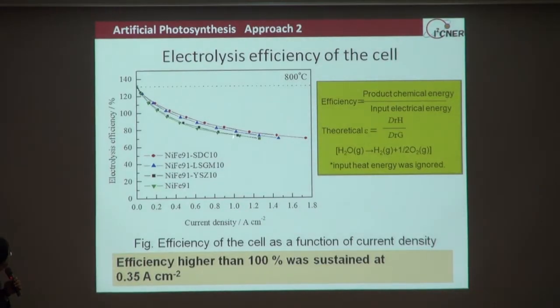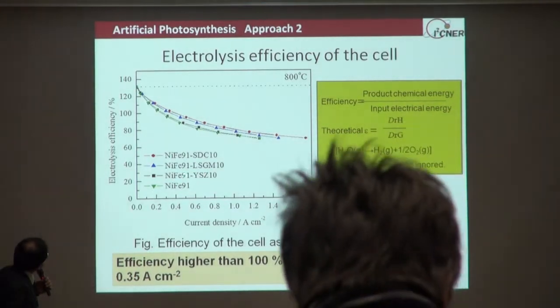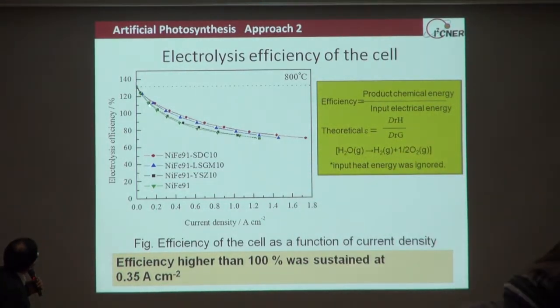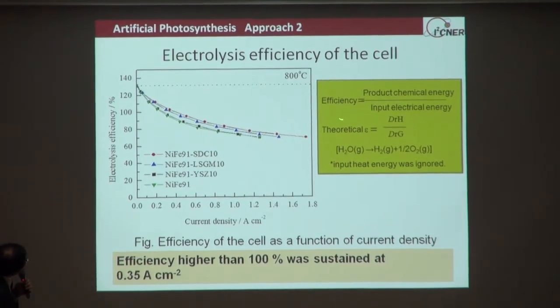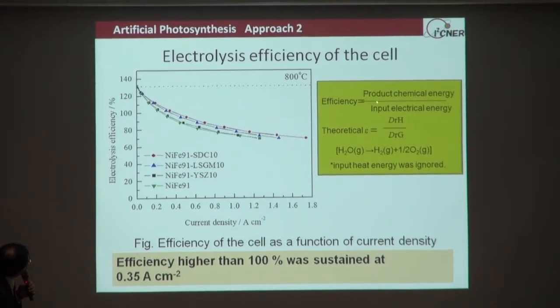And then this is the conversion efficiency. As you can see here, with increasing current density, the conversion efficiency decreases. But at the open circuit, we observed almost the theoretical conversion efficiency. Please remember that in these definitions, we do not add any heat. That is why the theoretical conversion efficiency is higher than 100%. With increasing current, Joule heat is generated, and the efficiency decreases and comes to 100%.